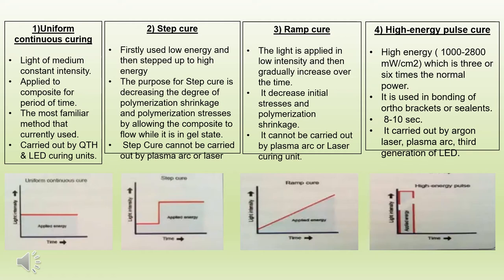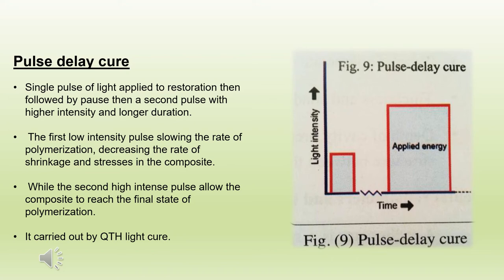High energy pulse cure uses a high energy of 1000 to 2800 milliwatt per centimeter square, which is 3 to 6 times the normal power. It is used in bonding of ortho brackets or sealants. In pulse delay technique, there is a pause between two pulses. The first pulse is of low intensity and short duration, followed by a second high intensity and long duration pulse.